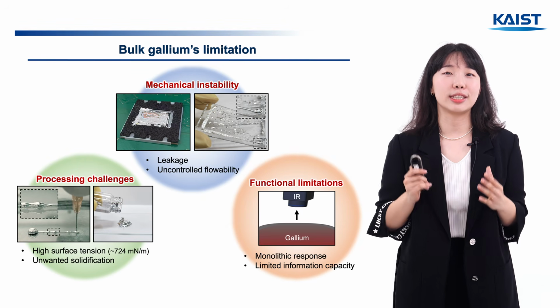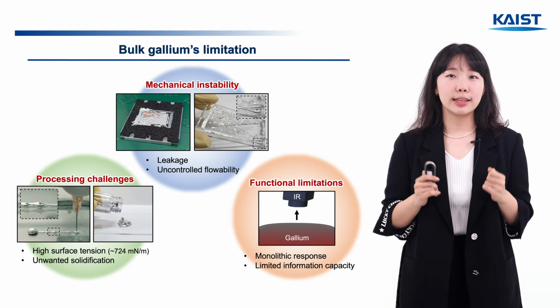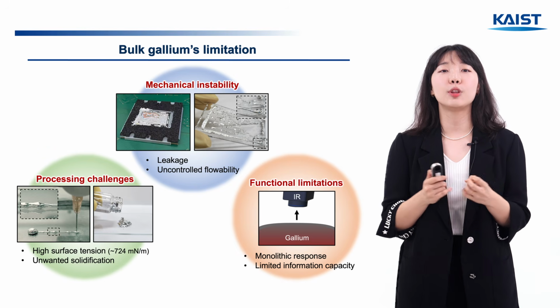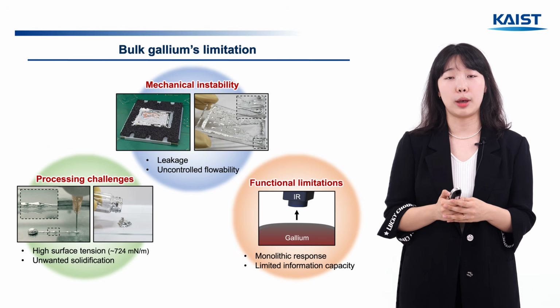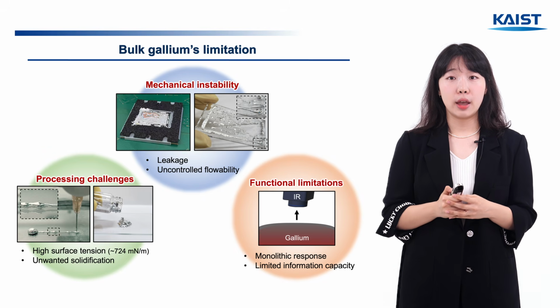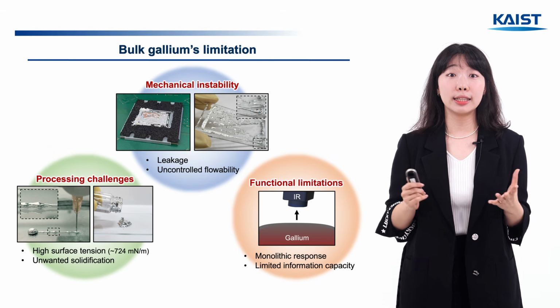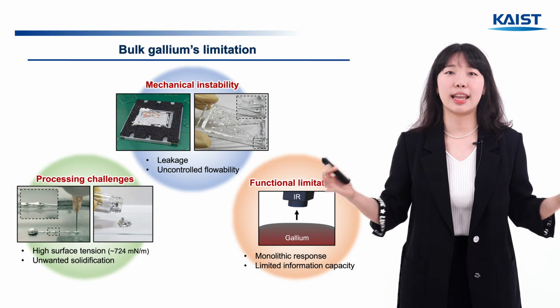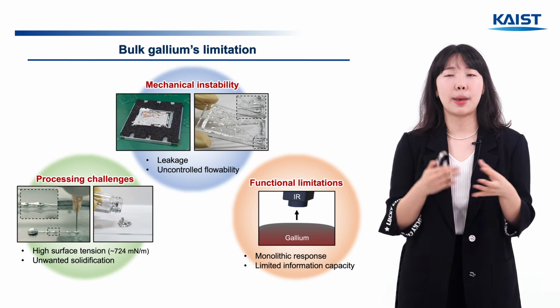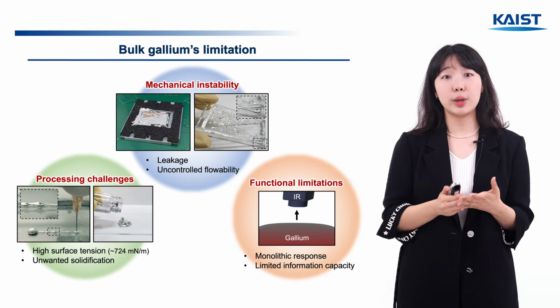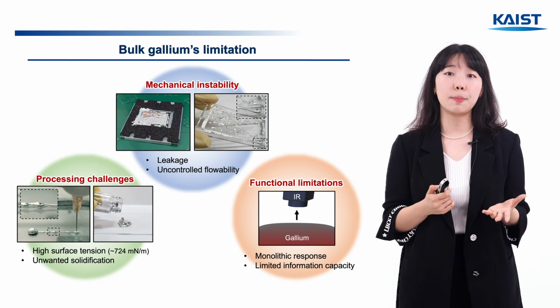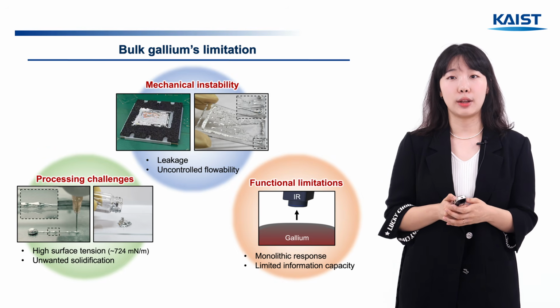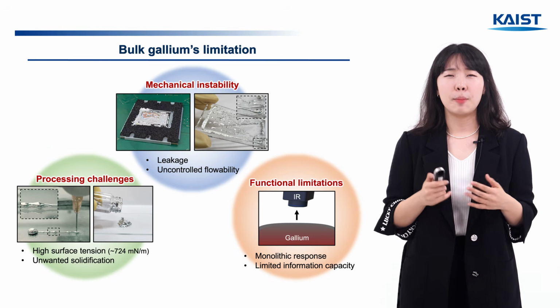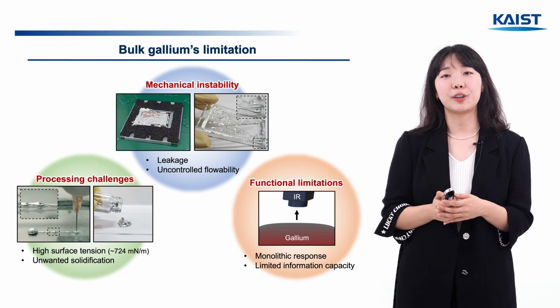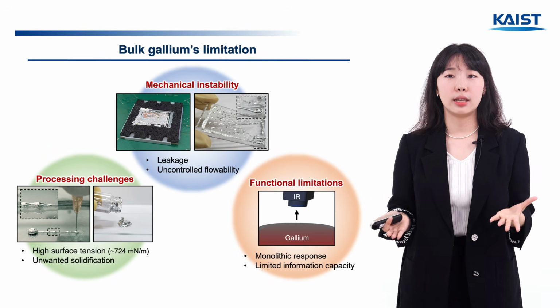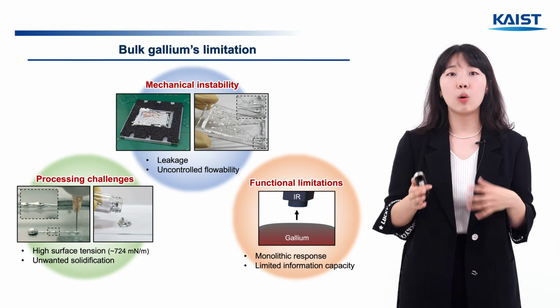Let's look at these in more detail. First, in its liquid state, gallium bursts and flows easily under even a small amount of pressure. Second, its surface tension is about 10 times higher than water. It means it tends to merge together, which makes patterning very difficult. And also, its low melting point near room temperature causes unwanted solidification during fabrication, making the process tricky. Third, as a single bulk mass, it is hard to control spatially or individually.